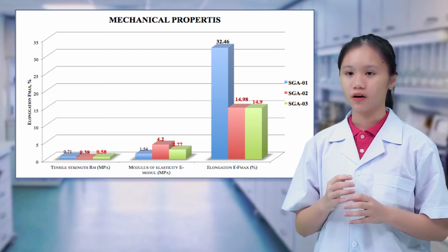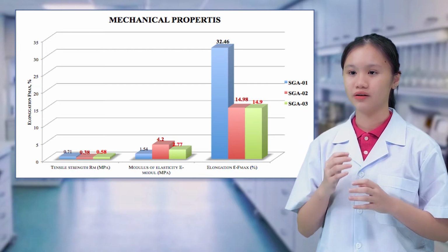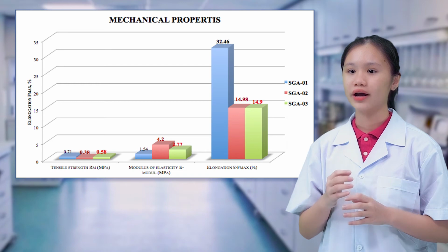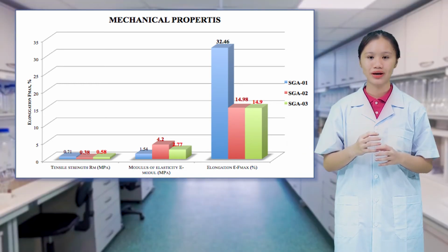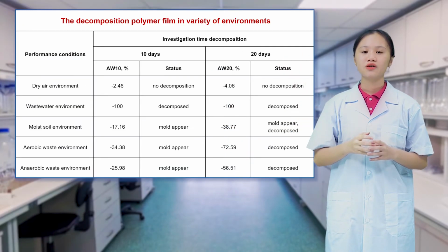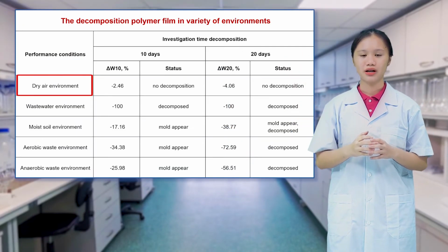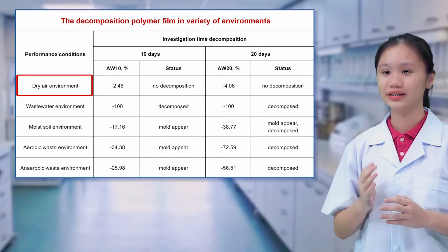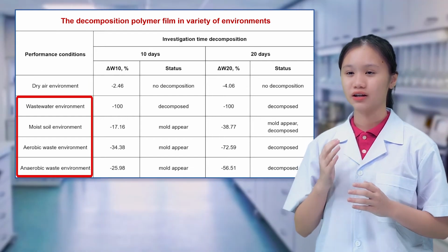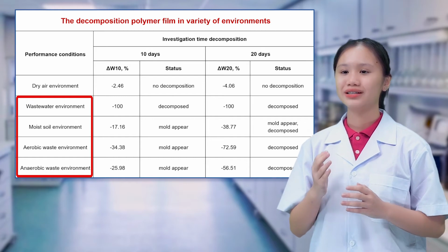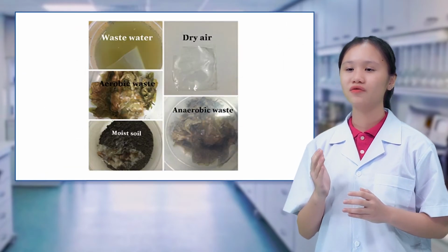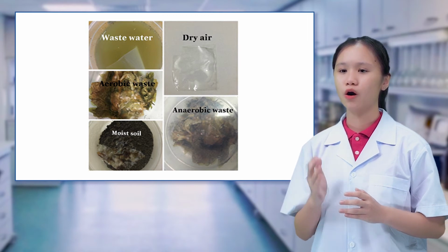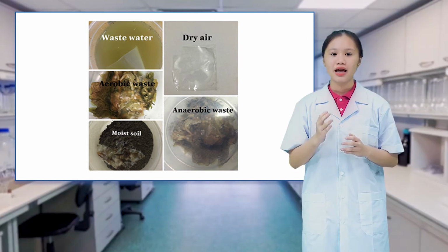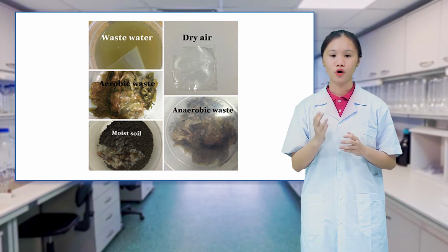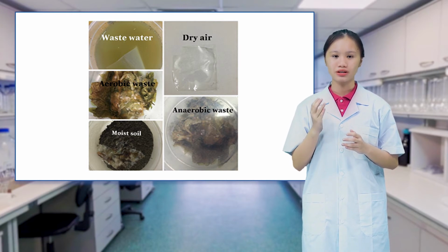The biodegradability of the synthesized polymer film was evaluated in a variety of environments, including dry air, wastewater, moist soil, aerobic waste, and anaerobic waste. The results are shown in the table. The process of degradation in the dry air environment is limited. No decomposition has occurred after 20 days. However, the polymer films had decomposed in the other 4 environments. Within 10 days, in most of the environments, the polymer film had developed mold, but it had already decomposed in wastewater, and in 20 days, it had completely decomposed in wastewater, moist soil, aerobic waste, and anaerobic waste conditions.